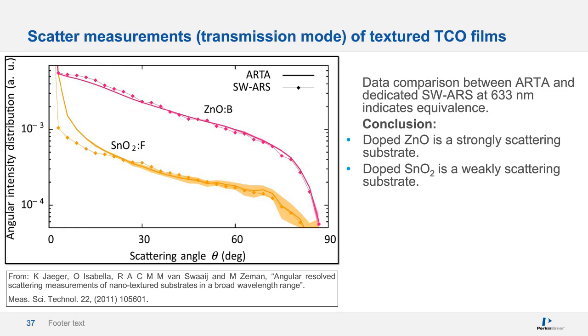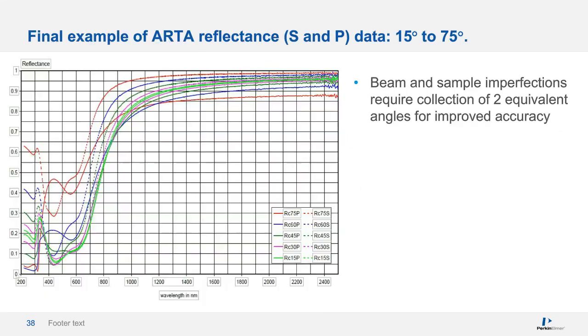Finally, here is some representative reflectance ARTA data for an unidentified glass sample from 15 to 75 degrees. Once again, the equivalent configurations are shown here to illustrate how easy it is to set up the accessory to perform the appropriate measurements.